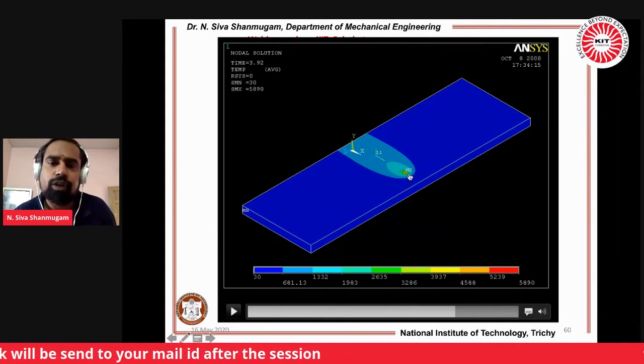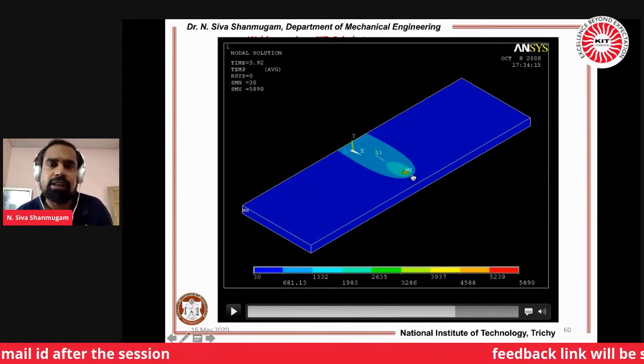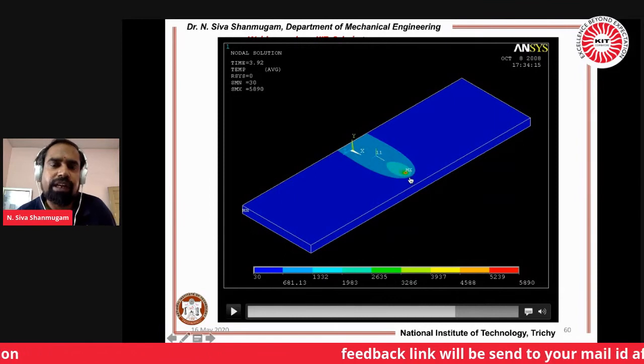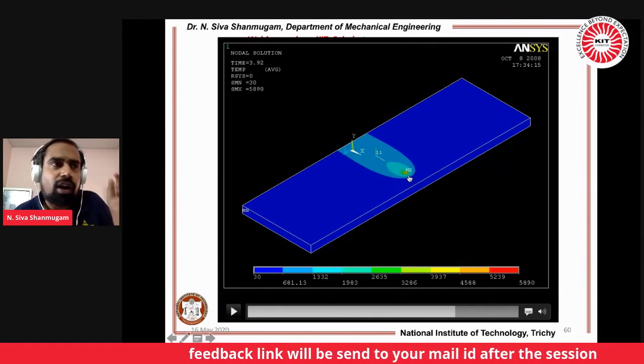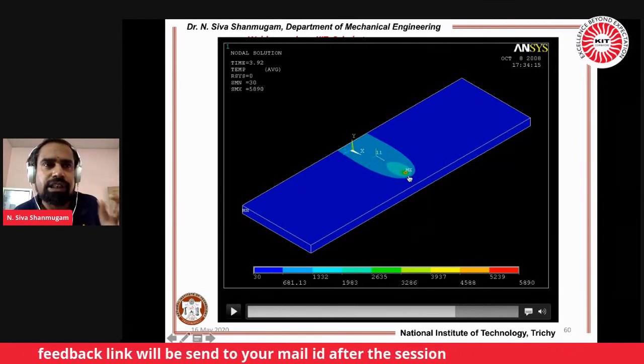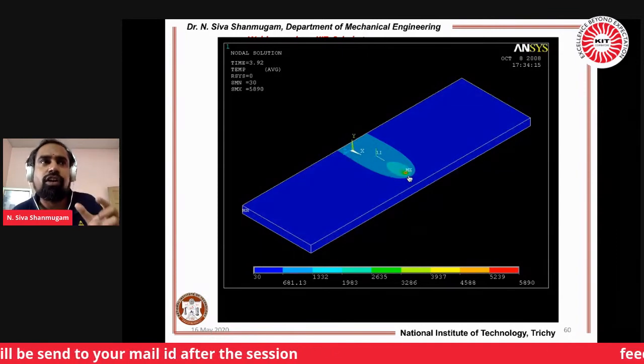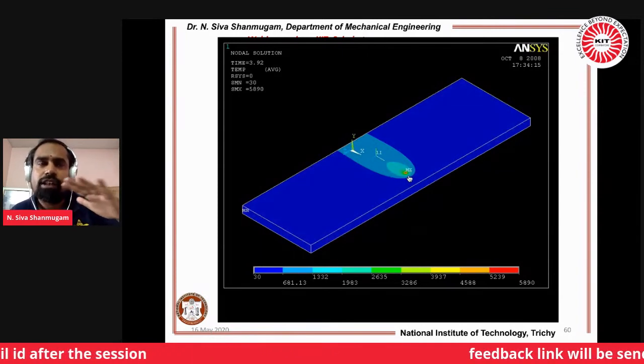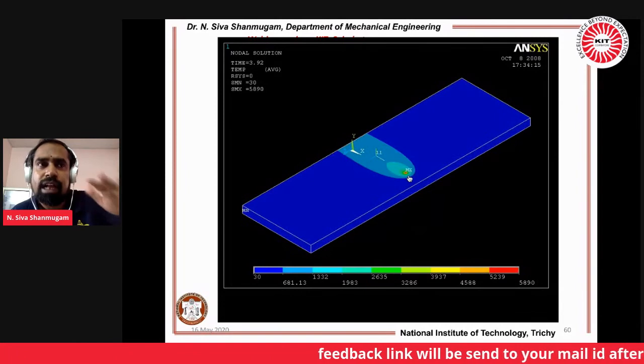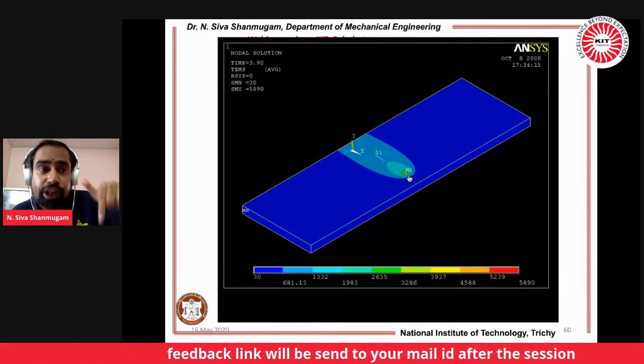When you simulate the commercial arc welding process, you are not getting this preheating zone. The preheating zone is very high, but it is a concentrated heat source. Most of the energy is getting into the material instead of staying on the surface. So surface energy is very minimal compared to the energy which is getting into the material.